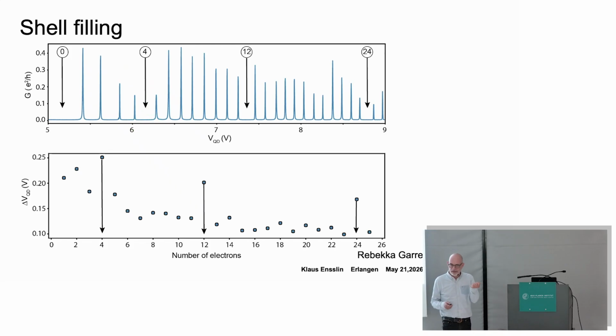So what is happening here? If you think of silicon, germanium, gallium arsenide, and so forth, if you have a small island, the ground state is something like an S-like state. Now this S-like state is twofold degenerate generally because of spin degeneracy. But now what happens in graphene is you have this additional degree of freedom, the valley degree of freedom. I told you there's the K and the K prime point in K space. That gives you an additional degeneracy, and you can read it off here directly. So the first 4 electrons, that's 2 for spin and 2 for valley.